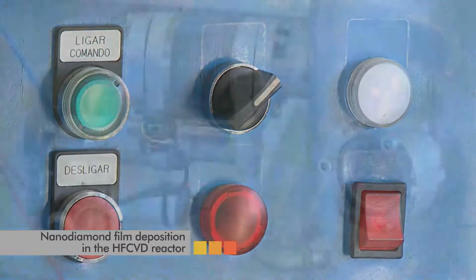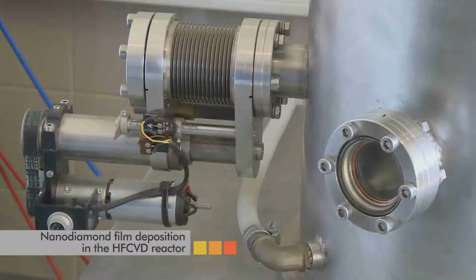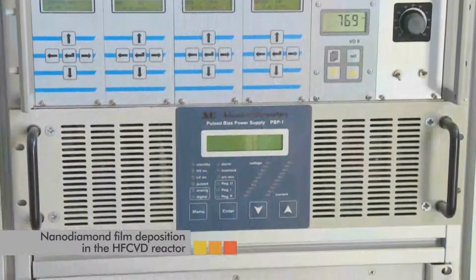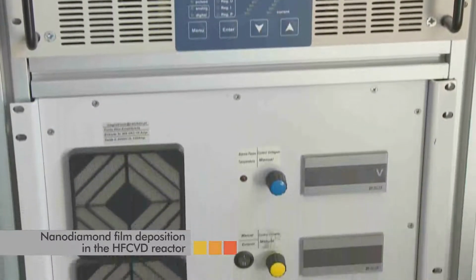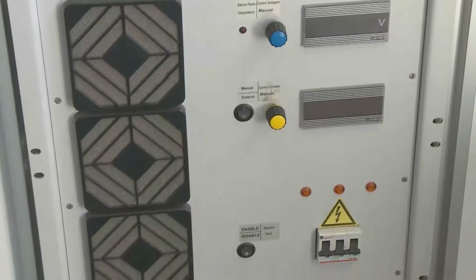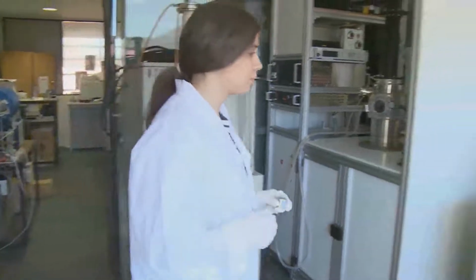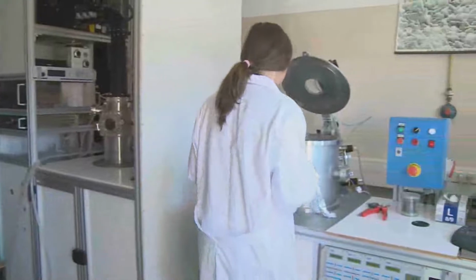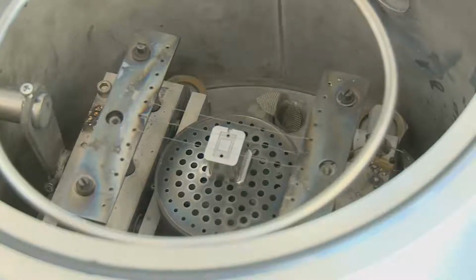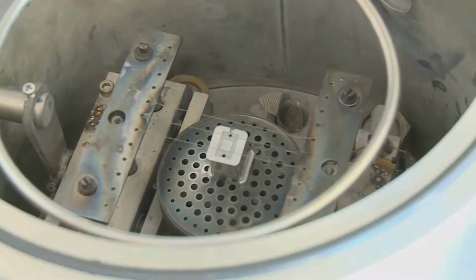Nanocrystalline diamond films exhibit high hardness, thermal conductivity, thermal shock capacity and low friction coefficient and can be coated into a vast diversity of substrates in a chemical vapor deposition reactor. After the preparation of the surface to be coated, where proper mask can be applied to grow the film according to a selected geometry, the moulding block is placed in the hot filament chemical vapor deposition reactor.